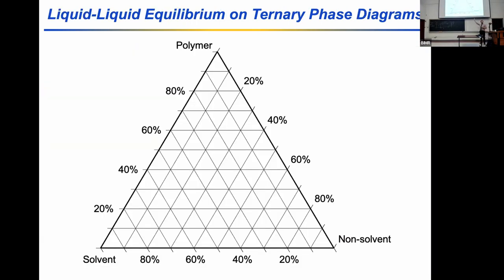They're often understood in terms of these ternary phase diagrams. And so I'll walk you through it. On the ternary phase diagram, each of the three corners is the pure material. Each edge of the triangle is a binary mixture, right? So that homogeneous polymer solution would sit on that edge of the triangle that's slanted from the bottom left to the top, right? And then as we move into the middle, we have three component mixtures that can be represented on this triangular plot.